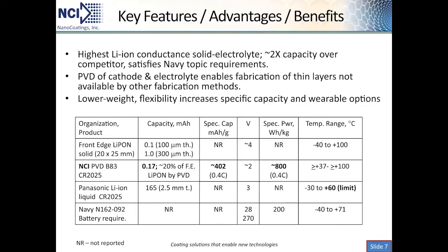The key features of our technology are shown in this chart. As I stated earlier, we're using the highest lithium-ion conductance solid electrolyte, lithium antiperovskite, as our solid electrolyte material. We're performing RF PVD processing of cathode and electrolyte layers, which enables the fabrication of very thin layers, typically 1 to 2/1000ths of an inch thick, which are not available by the other fabrication methods, including slurry preparation and spreading with a doctor blade. What this enables is the fabrication of very lightweight battery materials on flexible substrates, which increases the specific capacity and could even eventually be used as conformable wearables for the soldier.